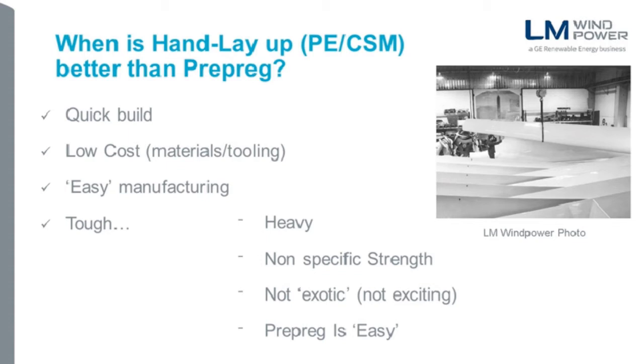When you then flick that over to infusion or prepreg or carbon or epoxy, then you definitely get a much lighter structure, but you don't get a comparable structure in terms of stiffness unless you add extra stiffening members or sandwich material or extra stringers or ribs in the structure. So there are some good examples where low-tech hand layup, random fibers, woven roving, fairly inexpensive, is the right approach, because you get this toughness and this stiffness, this toughness inherent of the thickness of the built-up cured ply thickness.